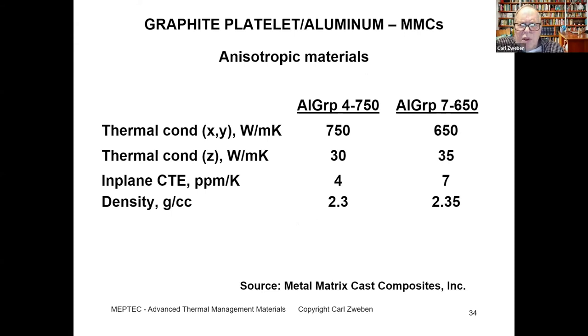To get higher values, we look at different reinforcements. Here we have graphite particles, graphite platelets, and you see two different materials, with thermal conductivities as high as 750 watts per meter Kelvin in plane. So it's approaching twice that of copper. And this material is also anisotropic and the through thickness thermal conductivities are in the range of 30, 35 watts per meter Kelvin. But you notice the in-plane CTEs are in the range of interest. And we also have a density advantage compared to aluminum. That's because the graphite particles have lower density than aluminum.